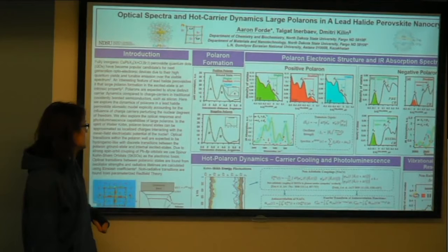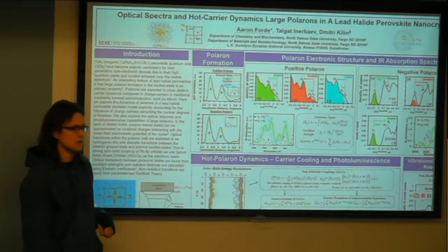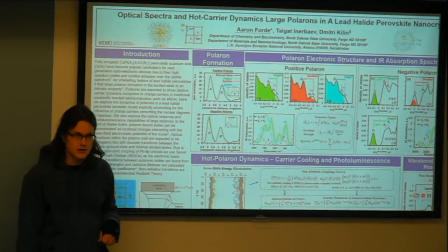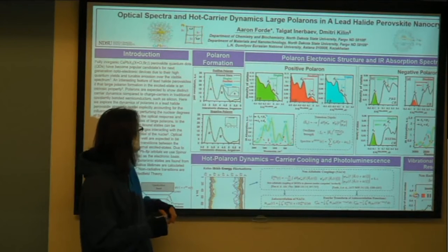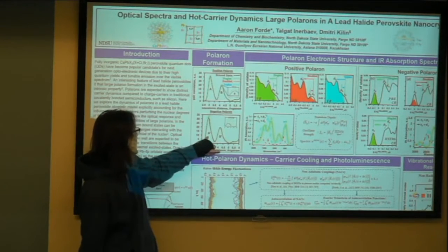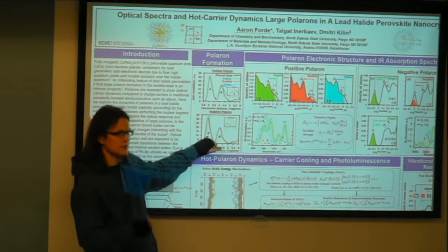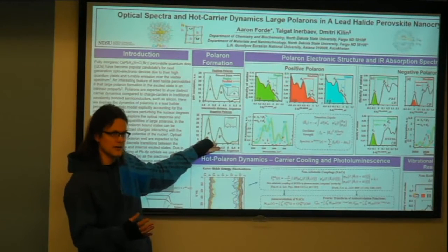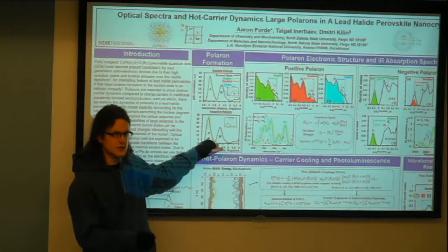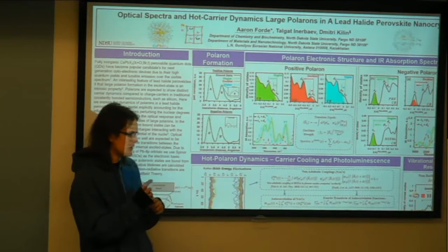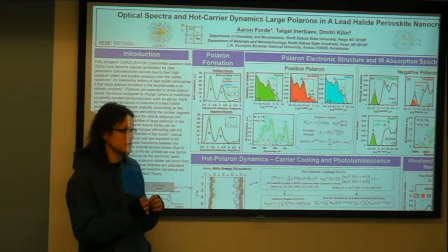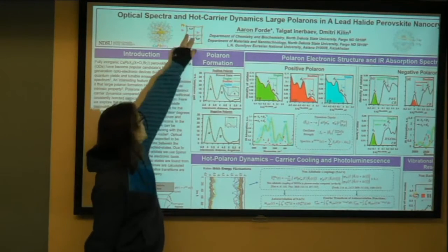And to describe that, we just used a simple oxidation-reduction type of framework. So you add an electron, that's going to slightly reduce the lead, because that's where most of the charge density is. So instead of being 2+, it'll be like 1 point something. So it has less ionic bonding strength to the bromine, so they just